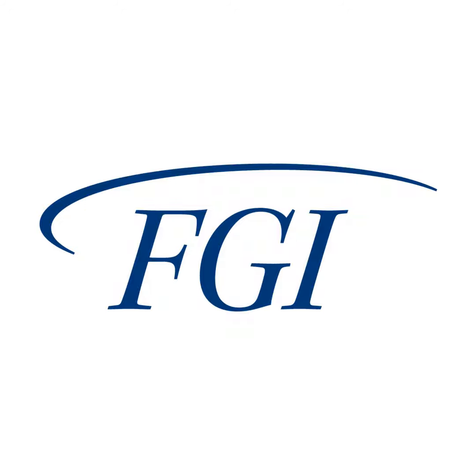It is better to use a bit larger, but 1 inch can be done. And you can obtain very precise, very accurate measurements. It's actually much better than AOS. That's another discussion we can have another day, but this test is far better for all the reasons than the classical bead test. Another point which is important is it's not all the products which have geonet laminated with a bonding strategy which involves heat. Some products are needle punched, some products are glued. It's really a matter of looking at what are the real questions.